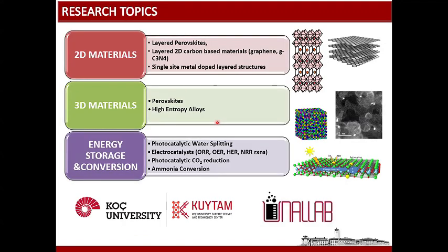So in my group, we are studying different materials. We are focusing on 2D materials, layered perovskites, or single metal doped layered structures. And recently, we started studying high entropy alloys as well. I will explain what it is. And we are trying to decrease the amount of noble metals by introducing them as single atoms on different structures, generally graphitic structures, or we are trying to disperse these noble metals as co-catalysts into the structure of the 2D layered materials to produce single active sites, which decreases the amount of noble metals and increases the number of active sites in the crystal structures.